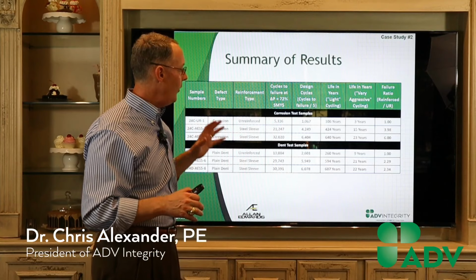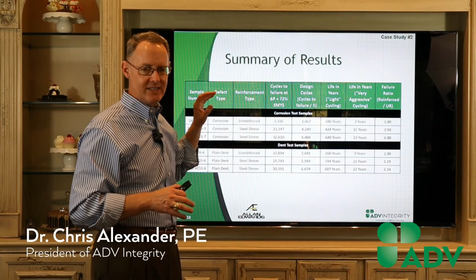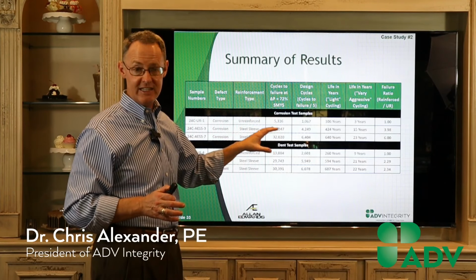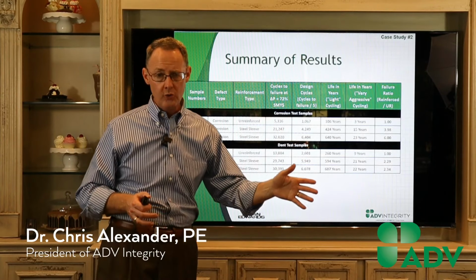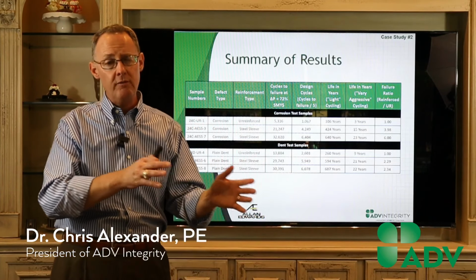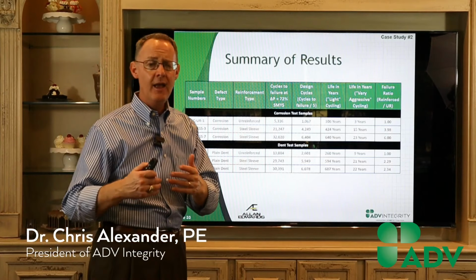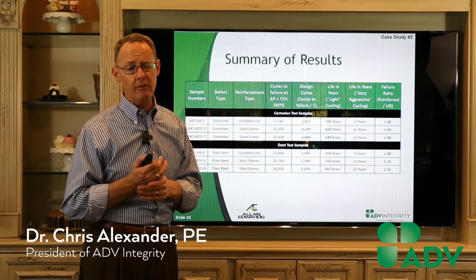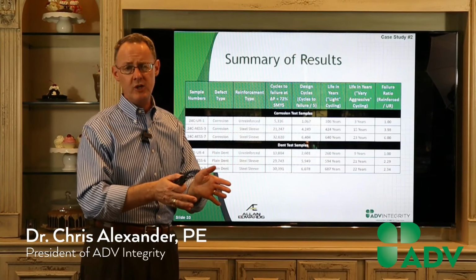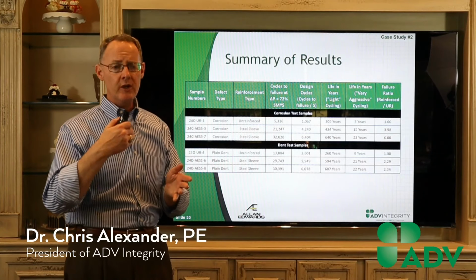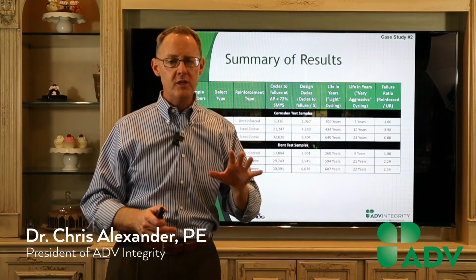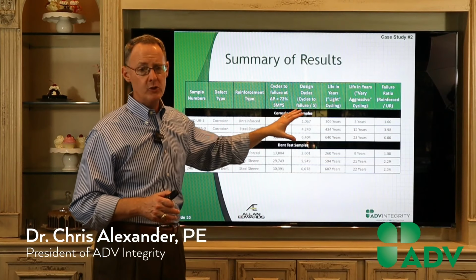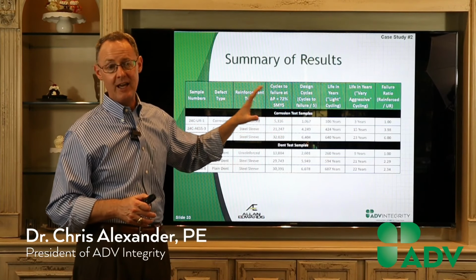But what we mainly showed is that you get a significant increase in fatigue life over corrosion and dents when you repair it versus when you don't repair it. And so that was the main thing that the operators that participated in this JIP said: just demonstrate to us that this works. The good news is all the operators who participated for the most part operate gas pipelines.